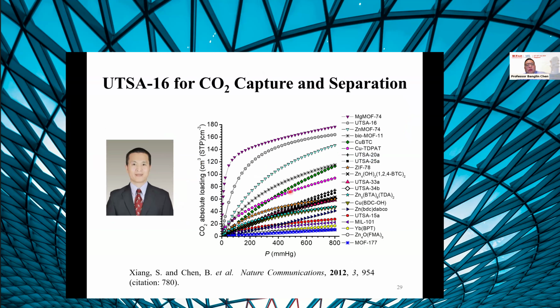And our breakthrough for MOF material for gas separation is this work, kind of accidentally discovered by my postdoc, now a professor at Fujian Normal University. And the material we call UTSA-16, you will see that compared with a large amount of different kinds of MOF material, this material is very unique. Quite high uptake for carbon dioxide capture at atmosphere and room temperature. However, also moderate enthalpy. This is good for regeneration. And only one other example is MOF-74, and this one is typically considered to have chemical bonding with carbon dioxide.